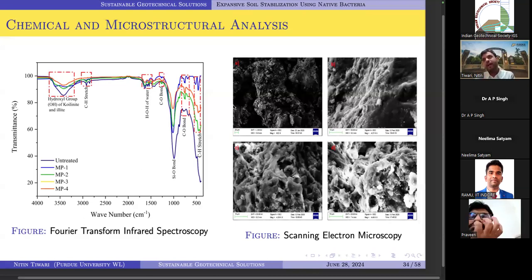Then we went to the SEM, scanning electron microscopy, and we checked this normal untreated soil. You can see the clay particles attached and there are a lot of cavities. But at the same time, after the treatment, 1 day, 3 day, and 4 day, you can see a lot of calcite content formation in the images. So it shows the treatment which we are talking about, the things happening, they are really, really working out inside the samples.